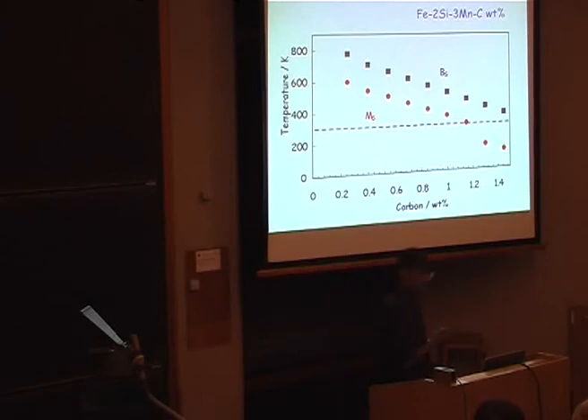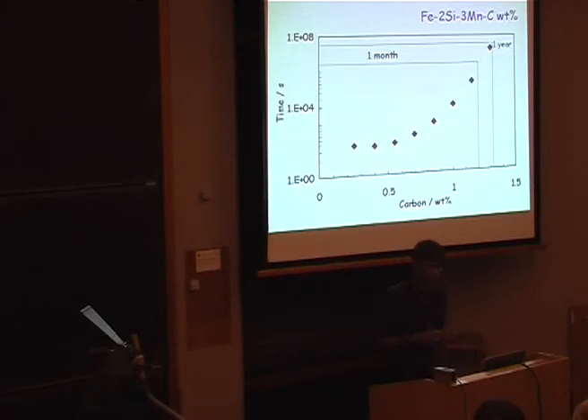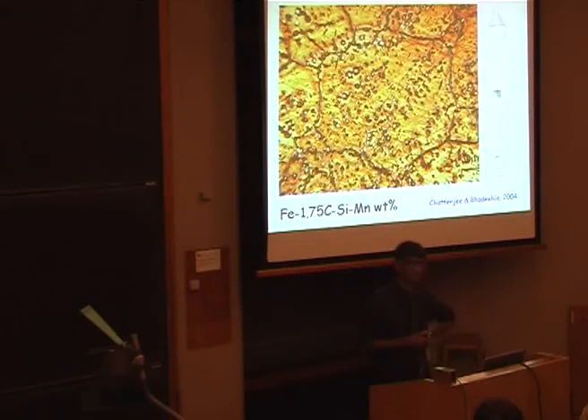But we also need to look at kinetics of transformations. And here is a calculated time taken to produce bainite as a function of carbon concentration. And here it would take about a century to produce bainite. So what we've done is we've made an alloy which will take 100 years to transform. Okay, and we've archived it. There's one sample in Cambridge, one in the Science Museum. It will soon be on display. And by observing the surface, we'll be able to say whether the theory is correct or not. In 100 years' time, I expect bainite to form there.